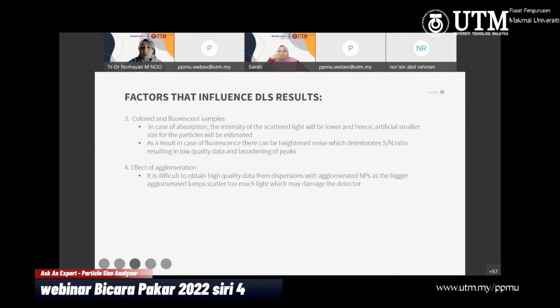And then if your sample is colored or fluorescent, in case of absorption, the intensity of scattered light will be lower and hence an artificially smaller size for the particles will be estimated. In case of fluorescence, there can be heightened noise which deteriorates the signal to noise ratio, resulting in low quality data and broadening of the peak. Sometimes you can see a notification in your result saying refer to quality report. In that report, they might say that your sample is fluorescent, so maybe you have to use another method to measure your particle size.